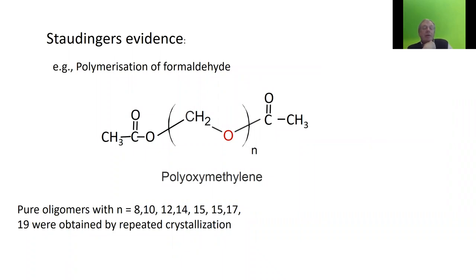He could do the polymerization of formaldehyde. If you add acetic anhydride to formaldehyde, you get this type of polymer, which has acetate end groups. When he did this polymerization, he carefully separated the different polymers, or oligomers, he got, crystallized them by fractionated or repeated crystallization, could investigate the single fractions, and by this develop the model of polymers and molecular weight distributions in these types of polymers. And by the way, this was also already the first topochemical polymerization, so that the formaldehyde polymerizes within the crystal.